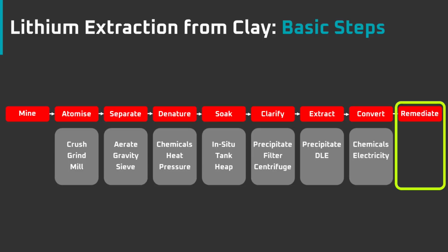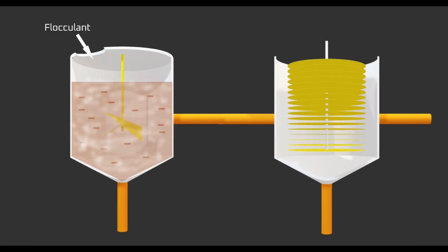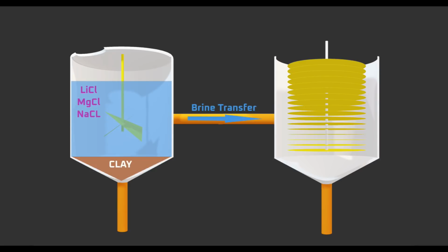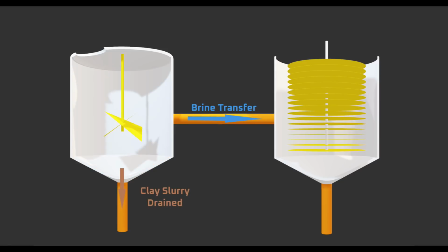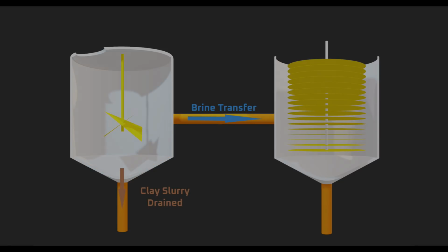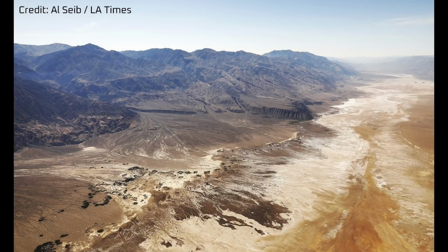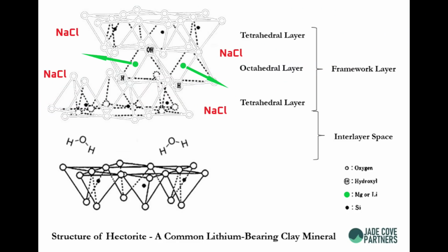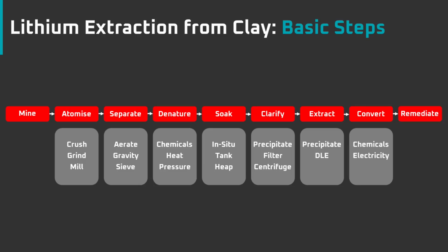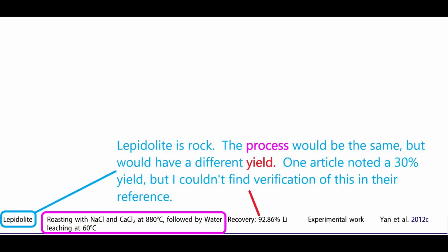Finally, remediation. The difficulty at this stage completely depends on Tesla's process. If, as I suggested above, they use a basic flocculation process that's used in municipal water supplies to precipitate the clay, and the metal salts don't precipitate with the clay, it might be relatively easy to return the clay back to the environment. I imagine it would be more complicated than I'm suggesting here and involve a significant amount of environmental assessment. Overall, the process I've laid out here for extracting lithium from the framework layer would be energy intensive, complex, use large amounts of chemicals, and would only extract about 30% of the lithium from the clay.